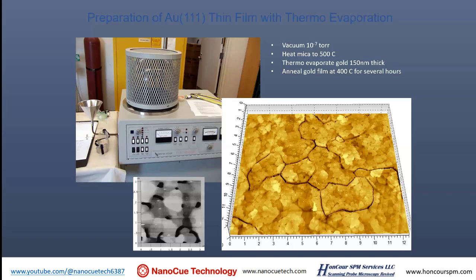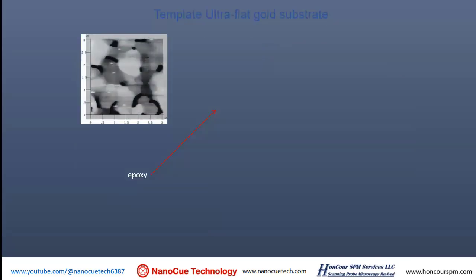So at the beginning of my career studying self-assembled monolayers, I would evaporate gold and do AFM on it right after that. So you evaporate gold every time you want to do an experiment. And those gold slugs in the year 1997 were $50 a piece. Now it's $200. So it's expensive. And then the gold is dirty. What do you do when the gold is dirty? There are actually many different ways to treat your substrate and reuse it, so you don't have to do the evaporation every day. It makes it cheaper. One way is what we call the ultra flat gold substrate template. So here's the procedure.